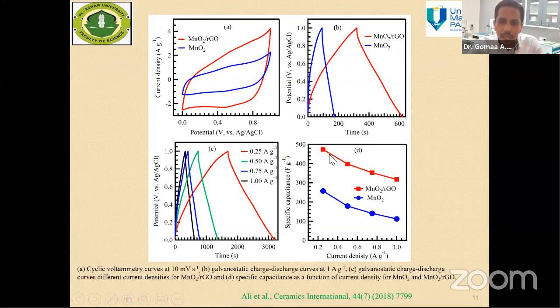applied current densities. And here, the synergetic effect of the combination between pseudo and electric double layer materials shows an increment of the specific capacitance to around 500 farad per gram. So the combination of graphene as a carbon double layer material with manganese oxide increased the capacitance of manganese oxide by around 2 times. Also, this work was published in Ceramics International 2018.